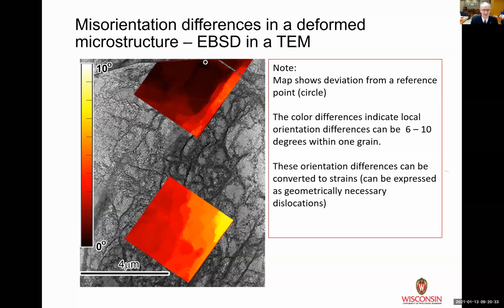If you go just less than a micron over, you're maybe at 5 degrees. And this is going to become important because this is getting us back to this idea of, can we measure the local strain inside a material? And can we use that information to give us insight into the mechanisms of hydrogen embrittlement? Right? But it's another technique we are now saying we are going to apply to try and understand what's happening in the material as we deform it. So this is new information that you can actually get.